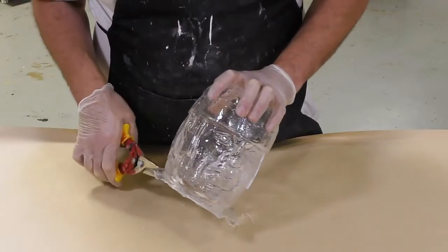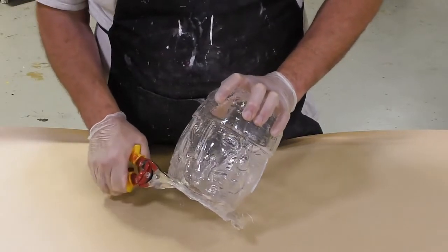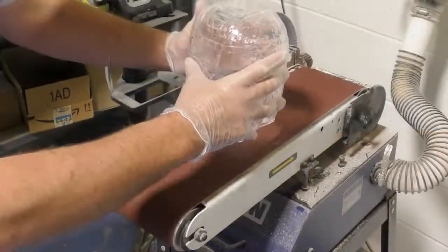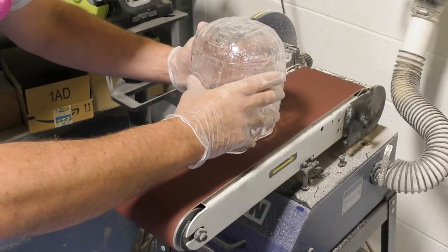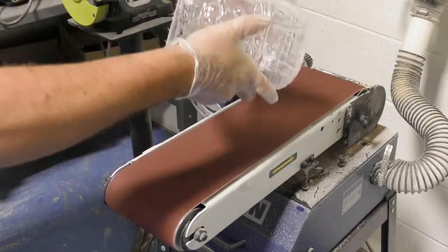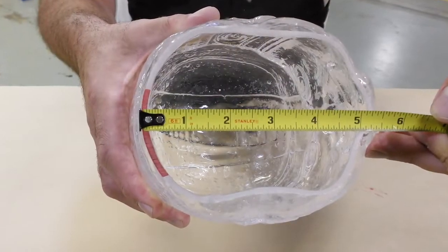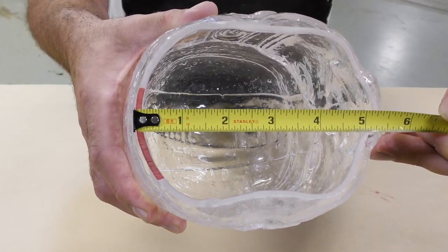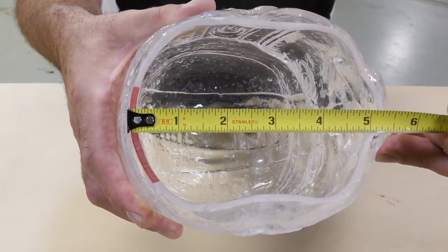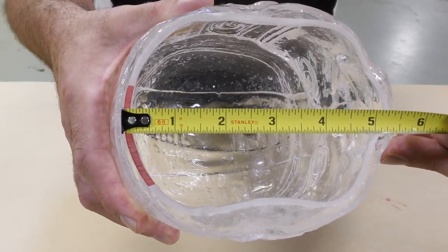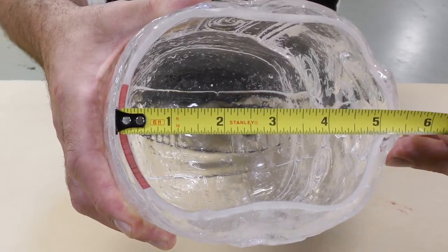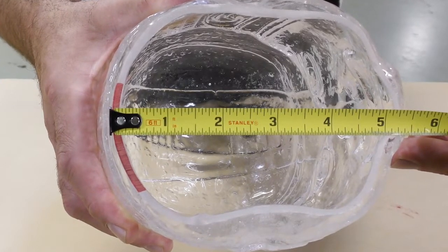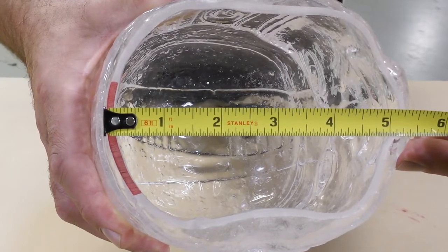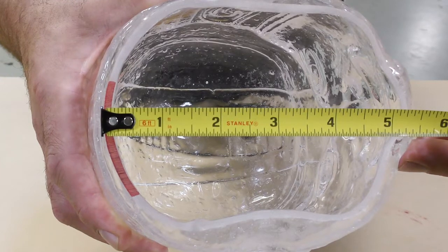To finalize our casting, we're simply going to trim away some of the flashing at the bottom of the casting itself. I can simply sand the bottom off to reveal an equal casting thickness all throughout the edge of our casting here. Now, the red mark you see underneath the measuring tape was put there by me so we can easily contrast the measuring tape against the casting thickness, which is about 3/16 of an inch or 4 to 5 millimeters. This assures us that we don't have a weak point around the bottom of the casting itself.